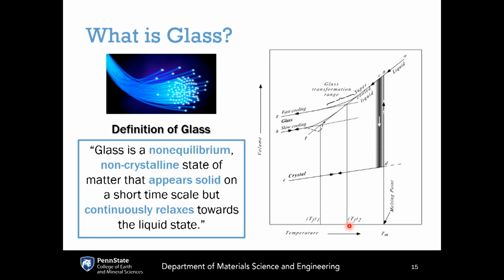This temperature, by the way, is what we call the fictive temperature, TF. Fictive literally meaning fictional. If you take a liquid and you cool it more slowly, it's able to stay in the metastable equilibrium longer, falling out of equilibrium at a lower fictive temperature, and therefore the structure of this more slowly cooled glass more closely represents that of the supercooled liquid at the lower fictive temperature. So this fictive temperature is an additional thermodynamic parameter. You need to know the chemistry, the pressure, the temperature, and something else to tell you the non-equilibrium state of the glass. The simplest of those is this so-called fictive temperature.